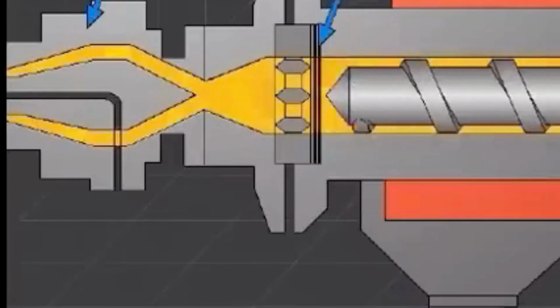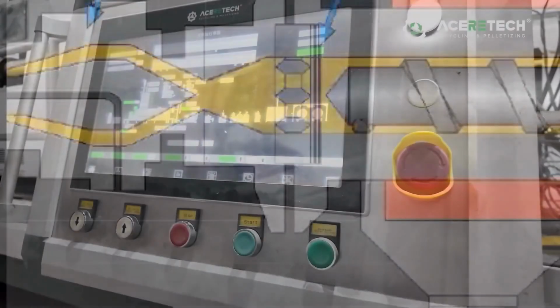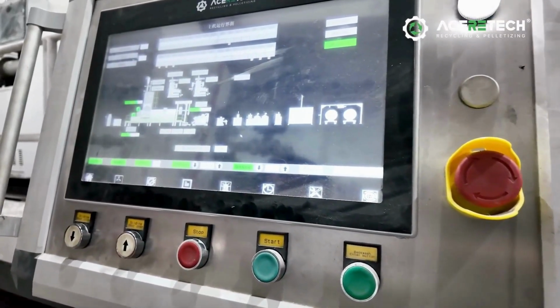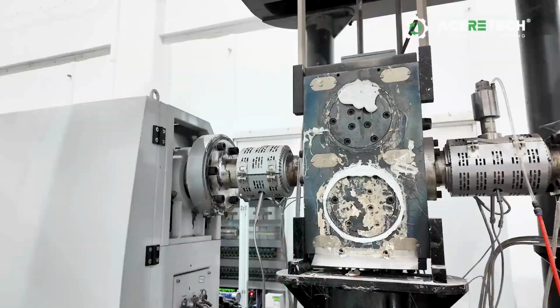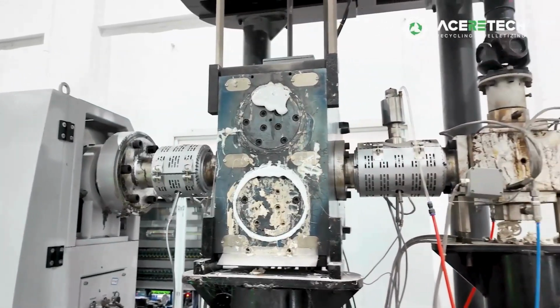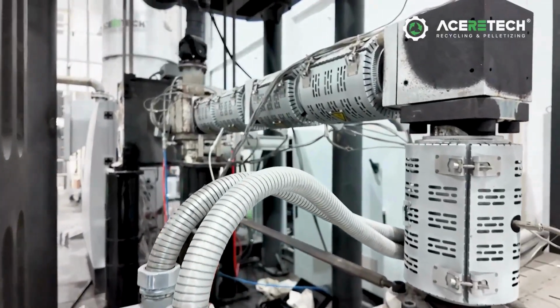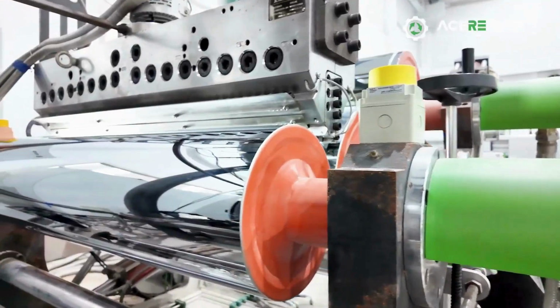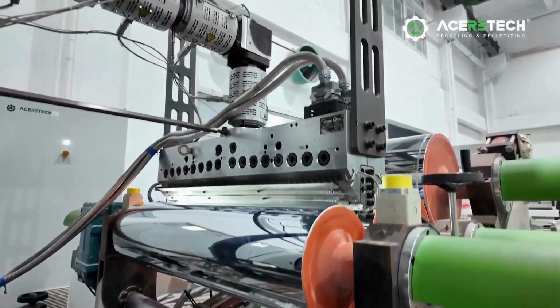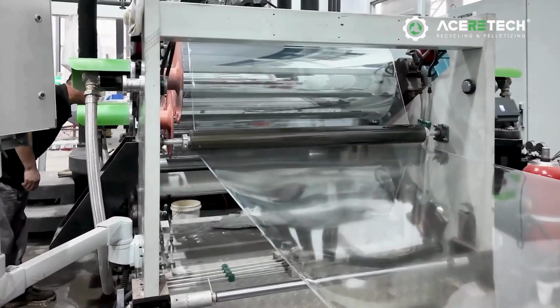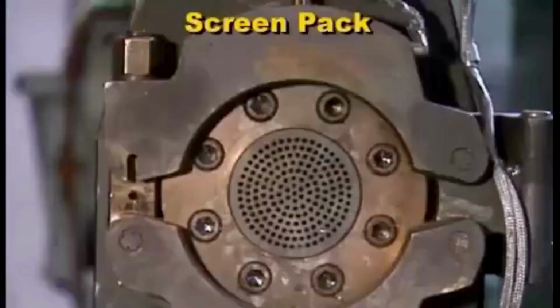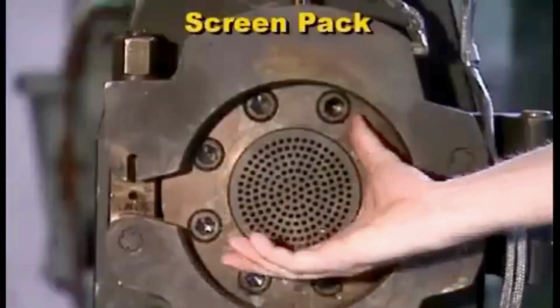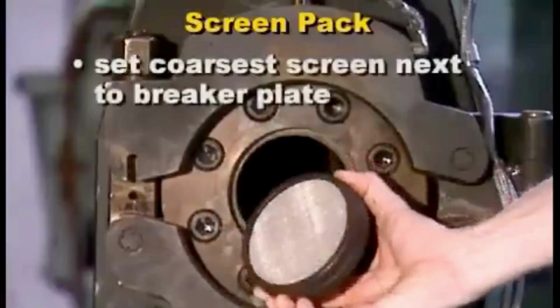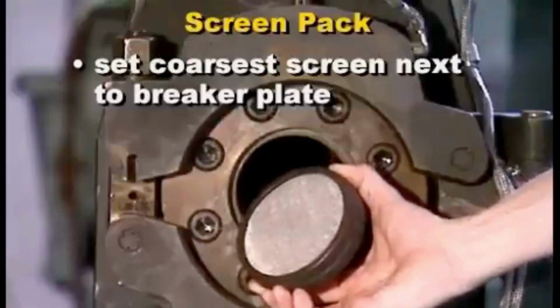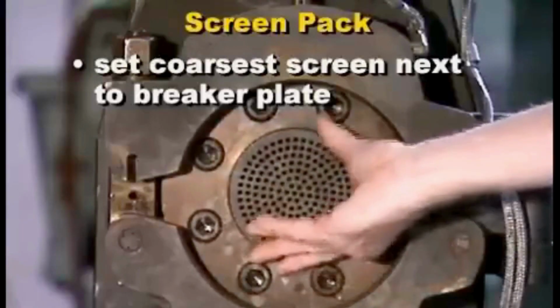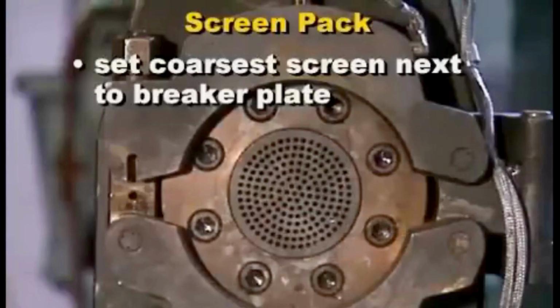As they advance, the material experiences both heat and shear, gradually transitioning from solid particles into a fully molten, homogenized melt. Devolatilization ports help remove any remaining moisture or trapped gases, preventing degradation and ensuring optical and mechanical consistency in the final sheet. Before the material exits the extruder, it passes through a melt filtration system that captures fines, dust, or contaminants introduced during grinding. By the time the PET reaches the die, it's a clean, stable melt, ready for precise sheet formation.